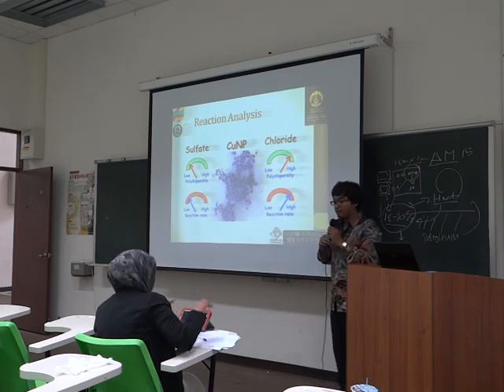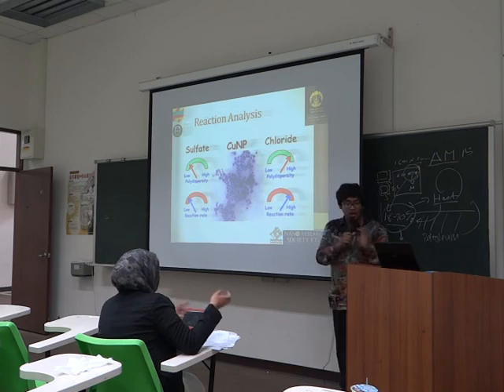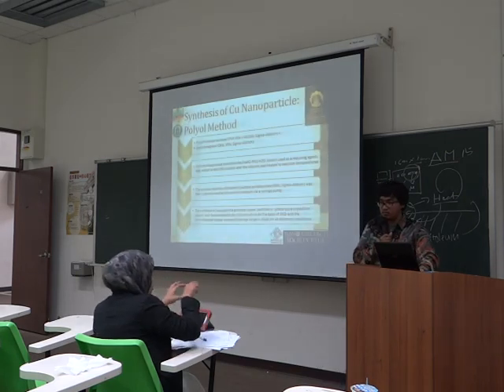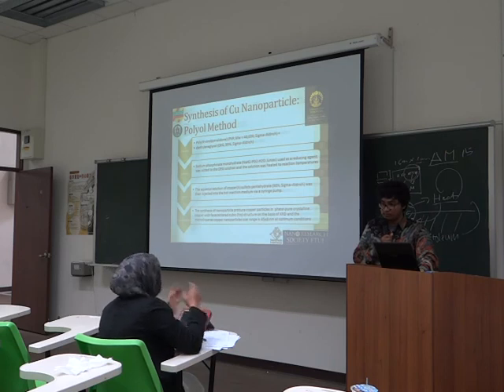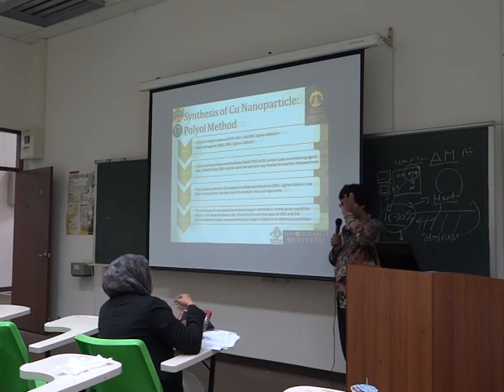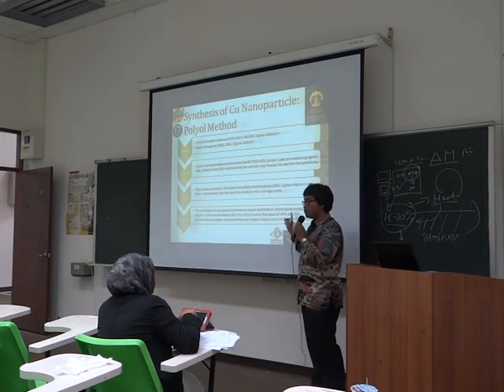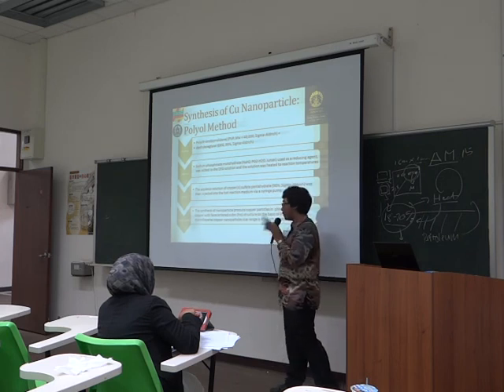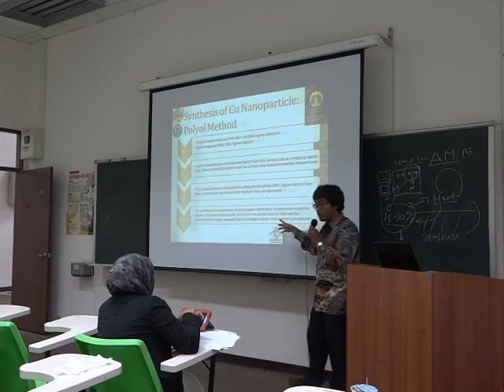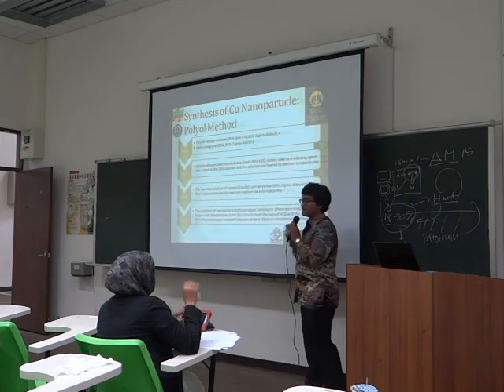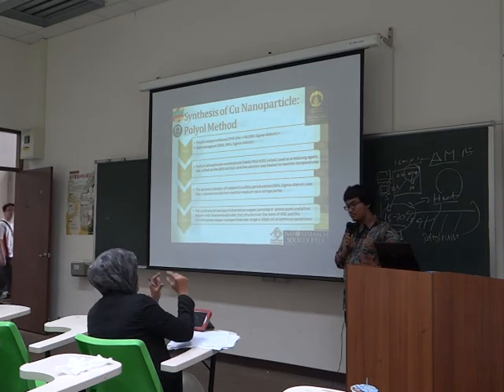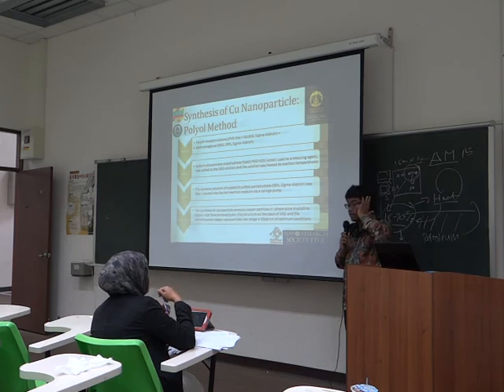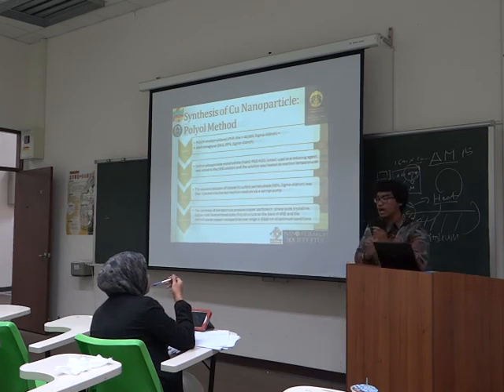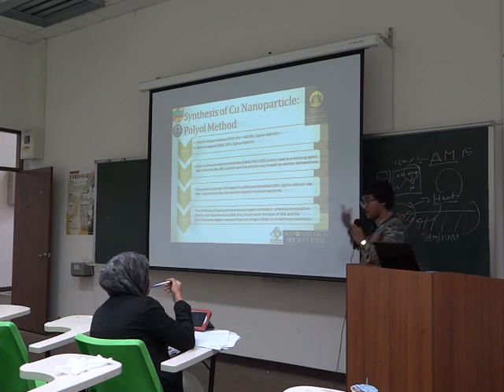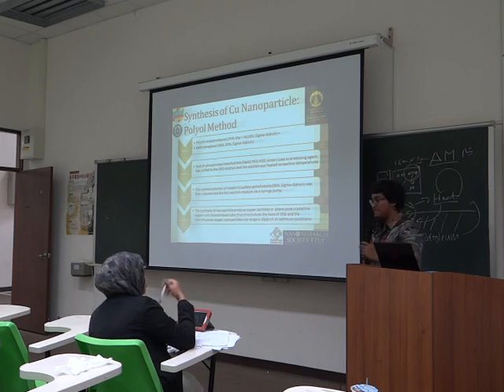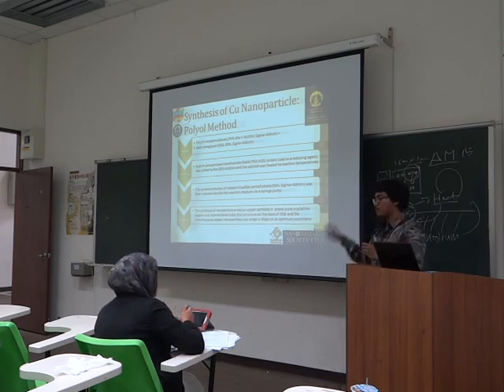So you didn't use a measurement device like TEM or SEM? I will use characterization, because this is nanoparticle, right? You need to make sure about the size. The characterization I use is XRD. The produced nanoparticle is a crystal of FCC, face-centered cubic, and XRD is to know the structure. For the size, we can use TEM or SEM, but it's much better to use high-definition SEM, because TEM is much more expensive. Yes, so you use SEM here? Yes, because 100 nanometers is possible with SEM, but for smaller sizes we can use TEM.